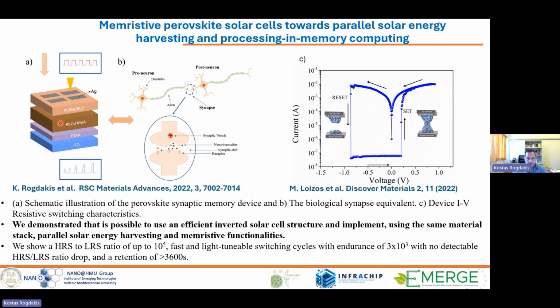This device can, of course, perform as a solar cell, but when we apply specific electrical bias, we can reset the system as a memristive memory element. So here from this IV, you can see very clearly two states. This is the low resistance state, and this is the high resistance state. So our devices can indeed perform as a memristor with two states, low and high resistance state, with a very good ratio, 10 to the 5. This is the difference between the low and the high resistance state. It's 10 to the 5.